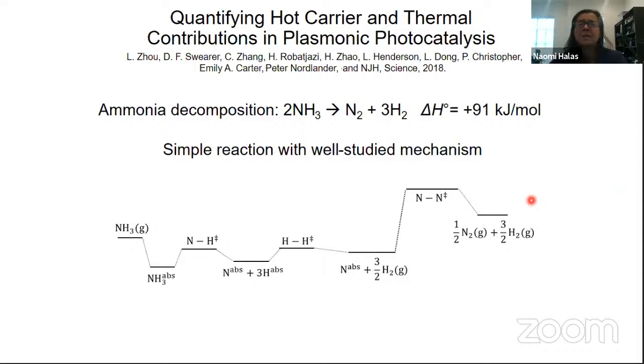So we also decided, there was a question that had plagued us since our very first reaction. And you probably can figure out what it is. As I have said now several times, when you shine light on a metallic nanoparticle, on a plasmonic nanoparticle, on resonance, you heat it up. You are always going to have large thermal effects, but you're also going to have hot electron generation or hot carrier generation. So how can you distinguish the two from each other? Is there a way that you can definitively say, yes, we have hot electrons produced, or no, we have a purely photothermal reaction, when in fact, in many cases, you're going to have both.